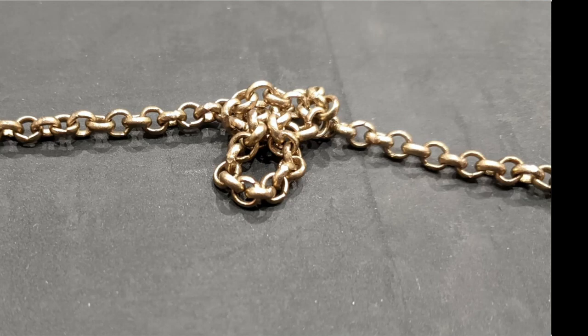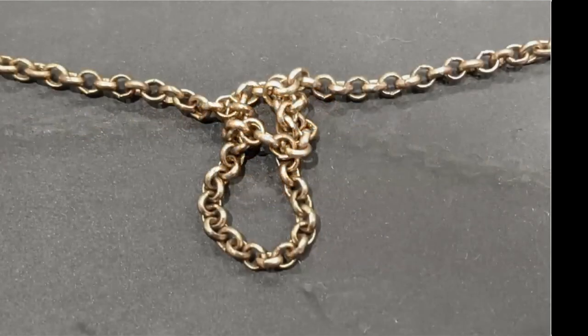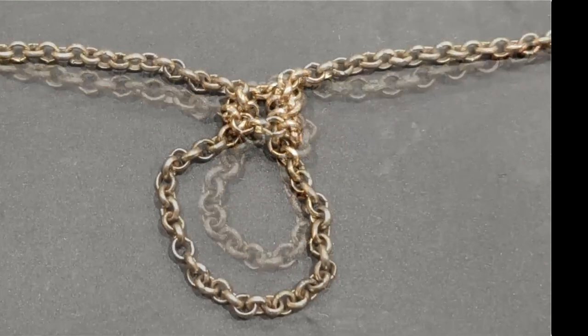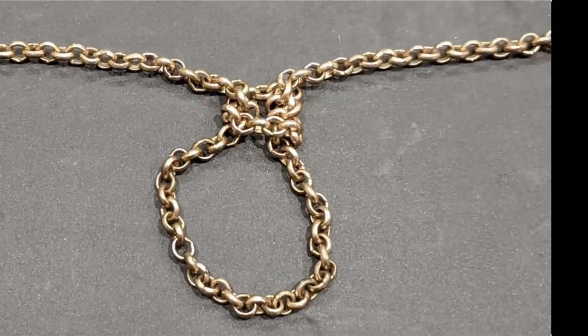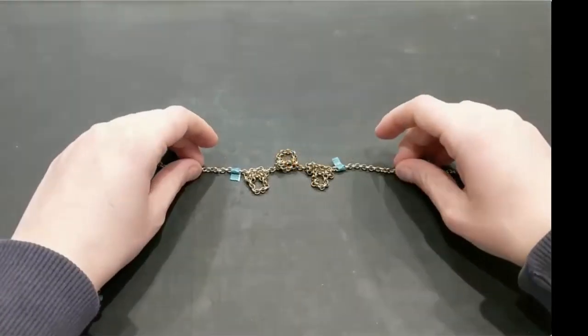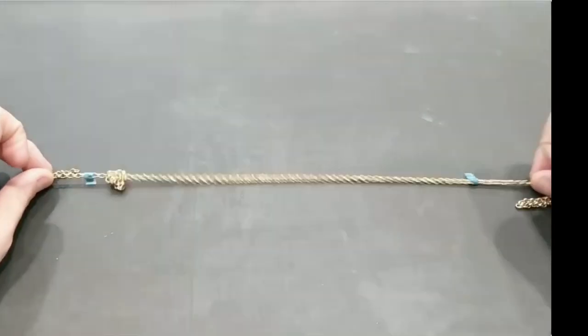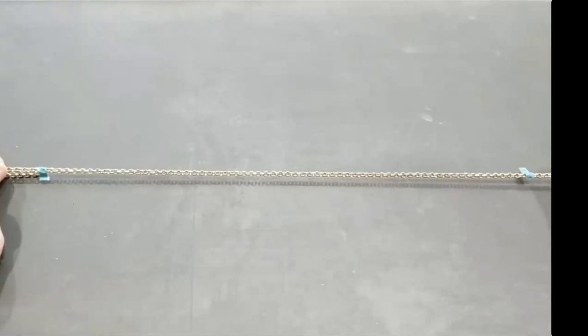So for example, take this concept of a little mechanophore loop that Patricia introduced, which inspires us to ask the question, so what if I made that loop a little bit larger, or made it at the molecular level larger still? And what if I had not one loop on each of these chains, but many, so that now as I pulled on that chain, those loops opening under force would lead to large changes in the length that a polymer strand could obtain and the overall stretch that it could accommodate on the molecular level.